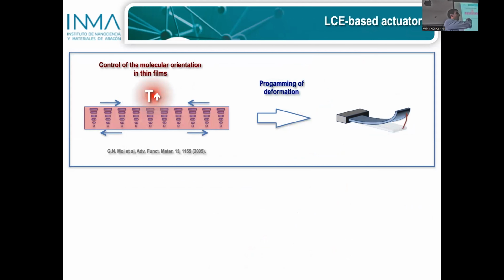Okay, but the previous slide was a liquid crystal elastomer fixed to a substrate, but much of the work that has been done in this field relies on actuators that are freestanding, not attached to a glass. And here you have a scheme of a TN, a twisted nematic layer, the same configuration that you saw in the display. You have a top layer with an orientation like this, and an orientation parallel to this direction, and a director in the bottom part leaving the screen.